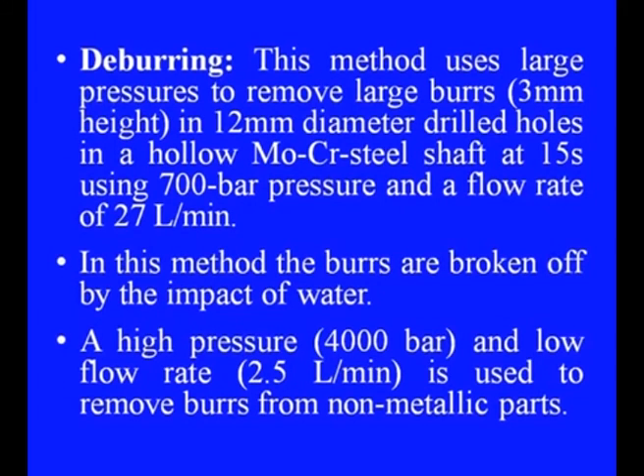Deburring is another area where water jet cutting can be used. Large pressures of water are used to remove large burrs, say for example 3 millimeter in height to 12 millimeter in height in a hollow molybdenum chromium steel shaft, and this can be achieved in only 15 seconds using 700 bar pressure and a flow rate of 27 liter per minute. In this method, the burrs are broken by impact of the water. A pressure as high as 4000 bar and a low flow rate of 2.5 liter per minute is used to remove the burrs from non-metallic parts.